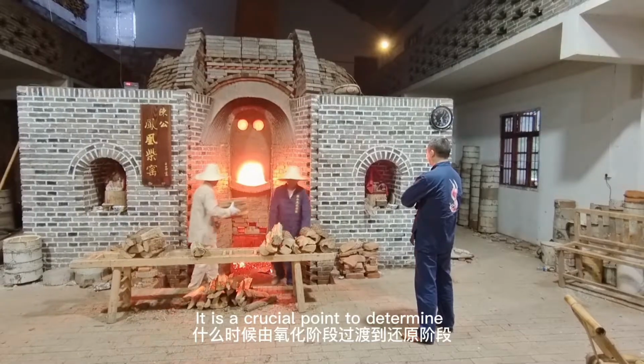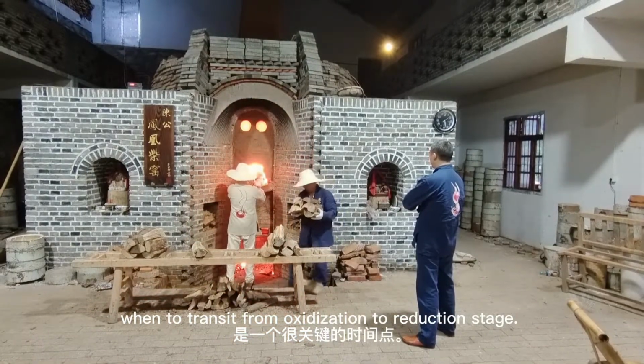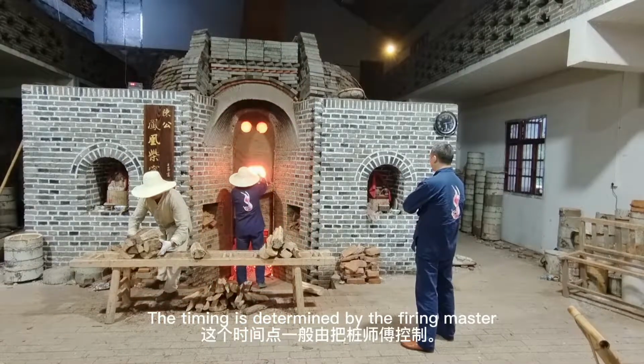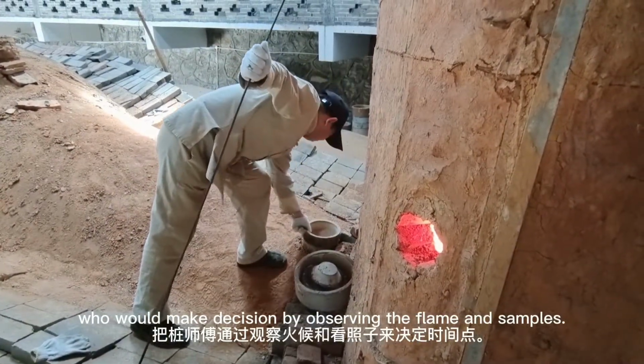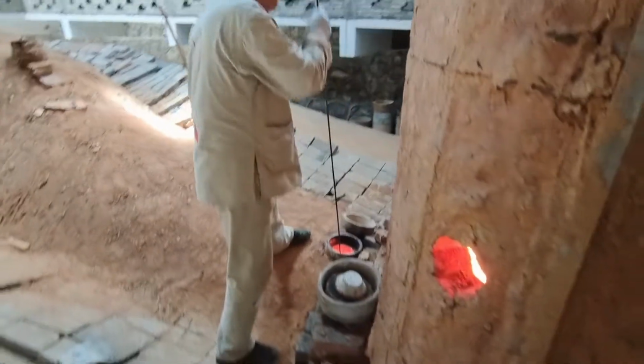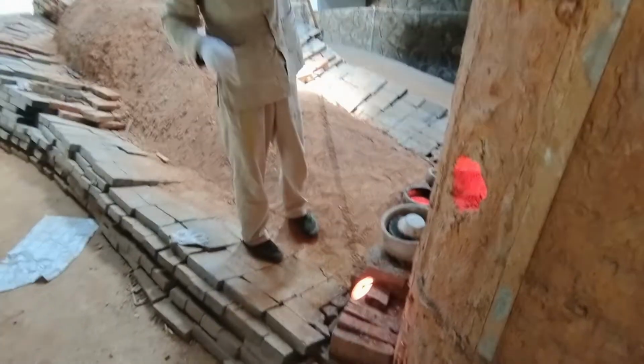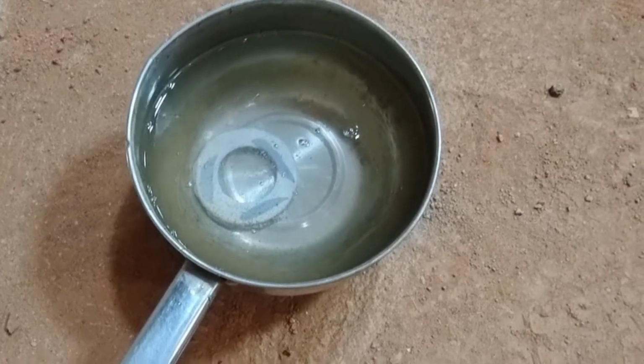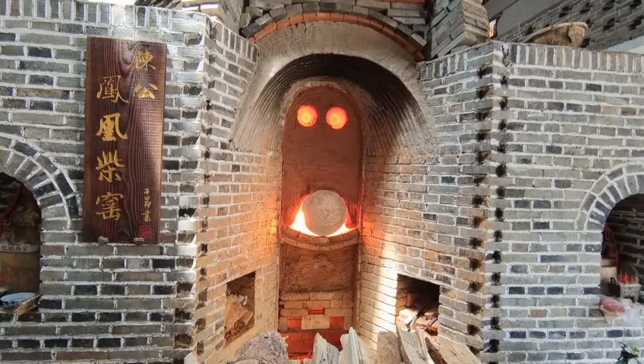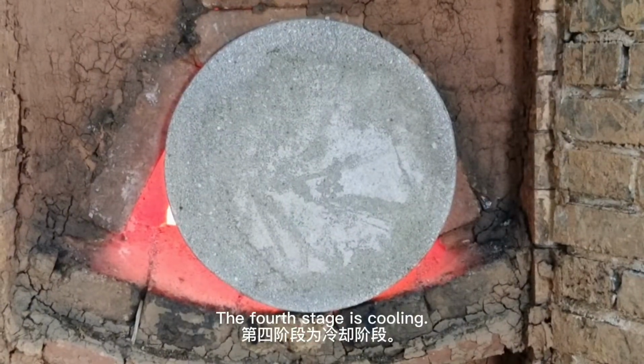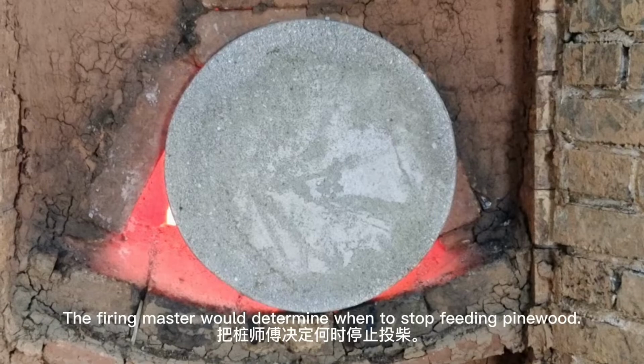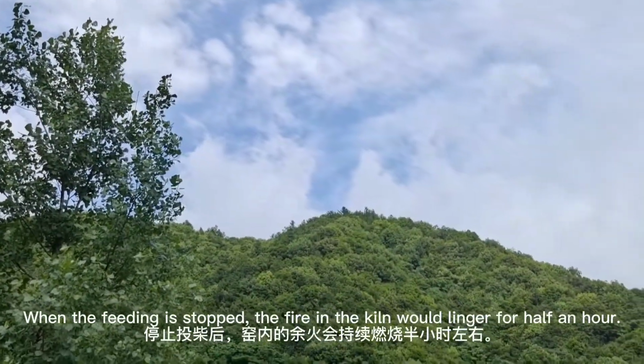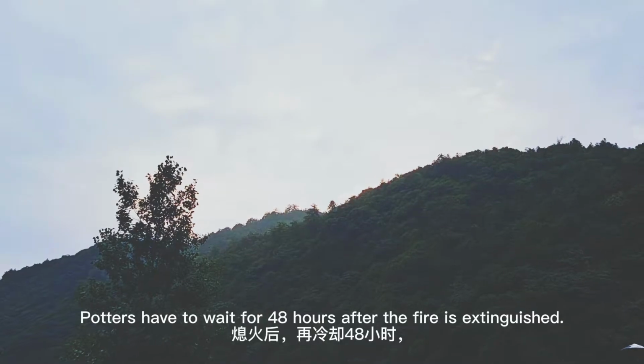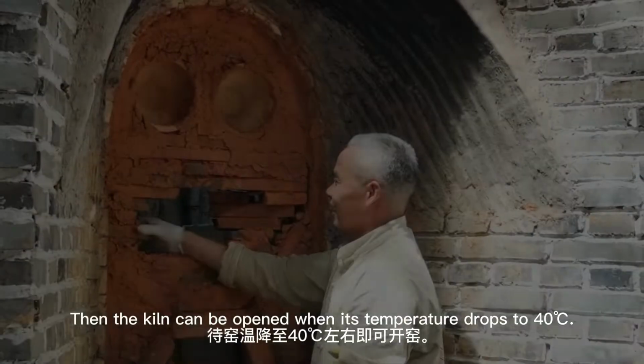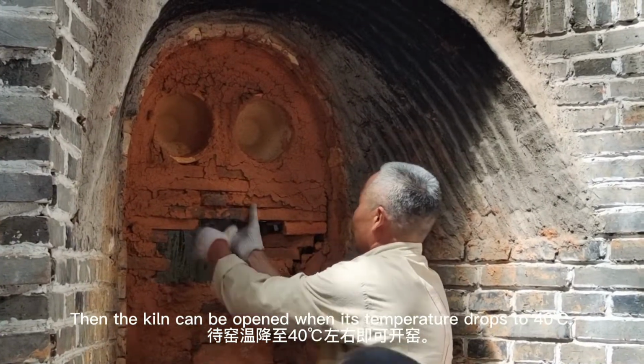It is a crucial point to determine when to transit from oxidization to reduction stage. The timing is determined by the firing master, who would make the decision by observing the flame and samples. The fourth stage is cooling. The firing master would determine when to stop feeding pinewood. When the feeding is stopped, the fire in the kiln would linger for half an hour. Potters have to wait for 48 hours after the fire is extinguished. Then the kiln can be opened when its temperature drops to 40 centigrade.